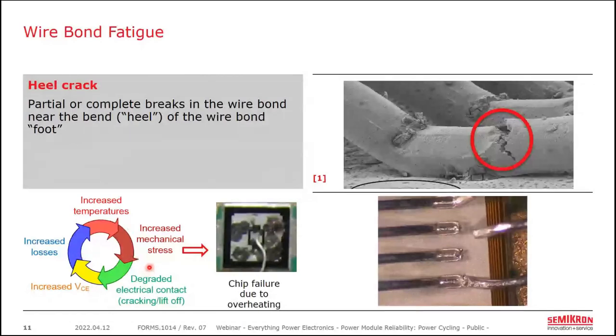And eventually that crack turns into a full break and the bond wire breaks off, as shown in this bottom photo. And like all power cycle failure modes that I'm about to show you, the end result, if left unchecked, is thermal destruction of the chip. And this means that in the case of power cycling failures in the field, much of the evidence of power cycling can be destroyed. Also, please note the use of my references here with number one. The references are all listed on the last slide of this presentation.